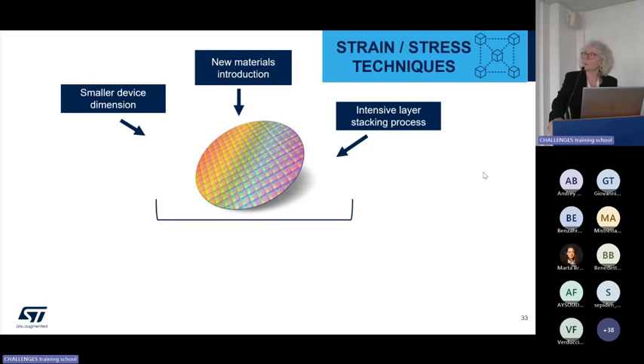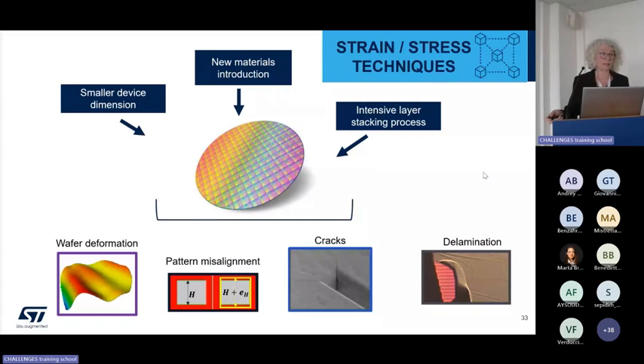What we can see is that we have a lot of new materials coming in nowadays, essentially with the More than Moore approach, with different thermal and mechanical properties. We do a lot of stacking, a lot of 3D integration, bonding one wafer on another, and even maybe triple wafers. All this will create stress because of the differences in mechanical properties. Sometimes we have overall wafer deformation, which creates issues for patterning, because the overlay correction will not be able to follow the deformation of the wafer. In the worst case, it can create cracks or delamination on the wafer.